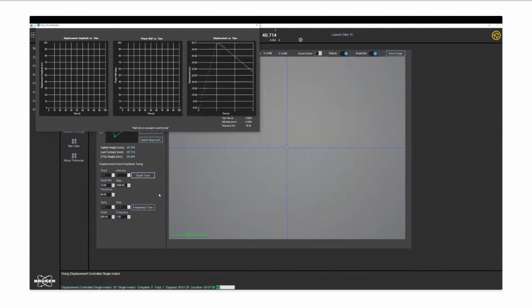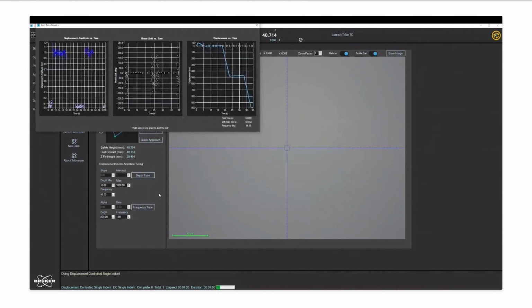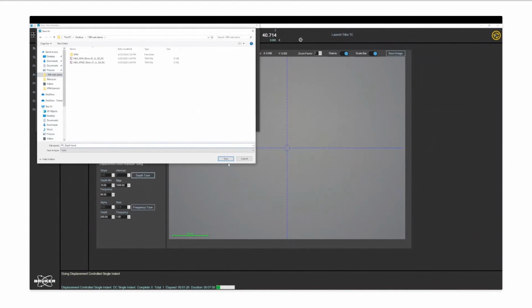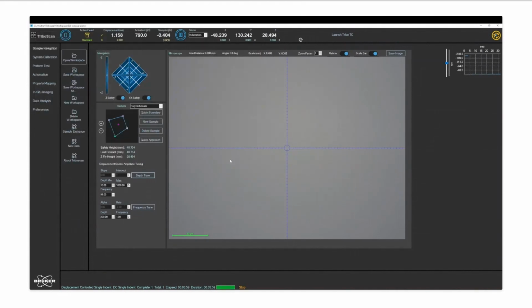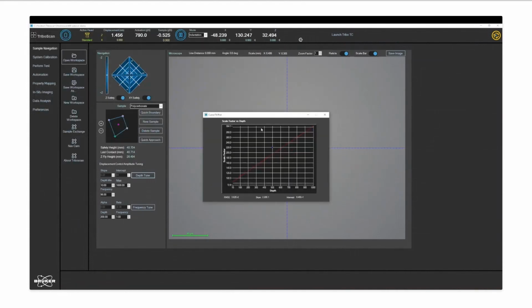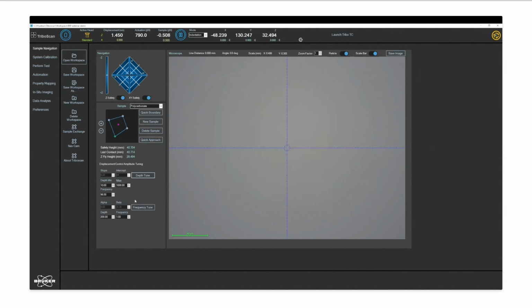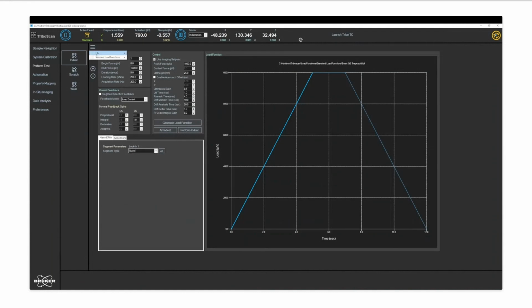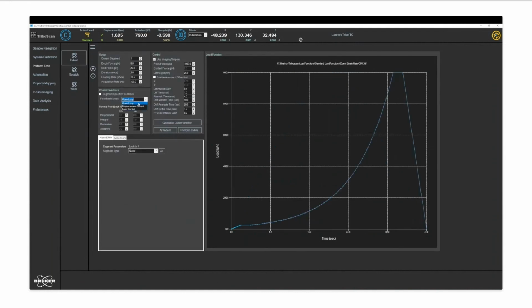A simple linear fitting is used in most cases. This tuning is then applied to the sample to maintain a set point as a function of depth during our continuous measurement of X, or CMX, indent. After this depth tuning, let's run a CMX test on the same polycarbonate sample in displacement control.